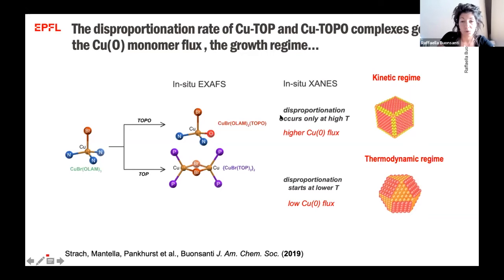And these two complexes disproportionate at different rates. Furthermore, the disproportionation occurs at different temperatures. Because of this, they generate a higher copper monomer flux in the case of the complex with TOPO, which establishes a kinetic regime, and we form nanocubes. In the case of the complex with the trioctylphosphine, we have a lower copper zero flux, which establishes a thermodynamic regime, and we obtain spherical nanoparticles.